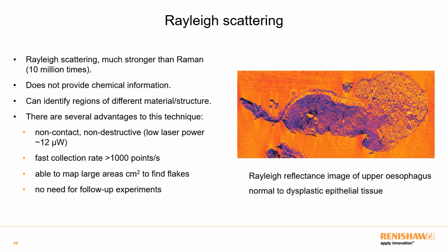So throughout this talk, we've talked about Raman scattering, which is a very weak form of scattering. Rayleigh scattering, the elastic part, is much stronger, about 10 million times stronger. So you can do a Rayleigh scattering image over a large area very quickly. The negative of Rayleigh scattering is it doesn't provide the chemical information like Raman does. But it can let us identify regions of different material and structure.